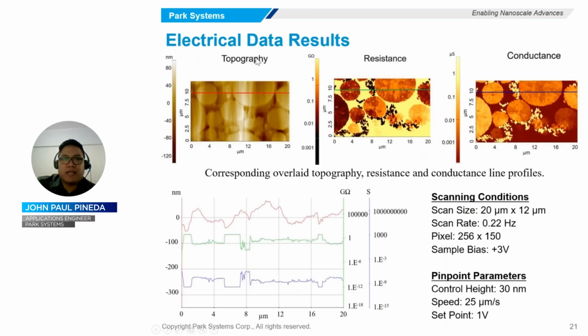So here are the electrical data results we have acquired in the experiment and the corresponding line profiles of each image. The topography image shows that the sample surface consists of circular shaped plateaus with diameters ranging from 2 to 8 micrometers. The circular plateaus with brighter colors represent areas with greater height, while the areas with darker color represent the low-lying areas.